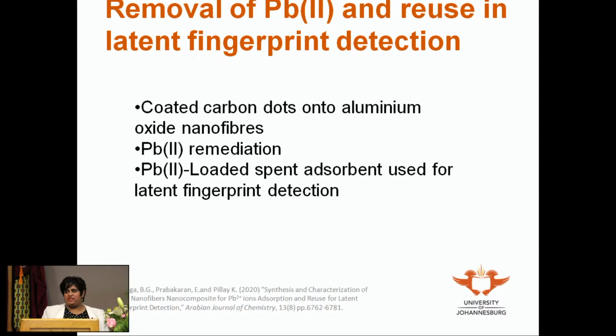Now, this has some new meaning for environmental remediation in that it can enable one to kill two birds with one stone. You're creating your adsorbent that can remove the metal ion. Then once the metal ion is entrapped on the adsorbent, it can serve as a photocatalyst to break down the organic material. Then in another parallel study, we cross-pollinated our water and forensic research. So we developed carbon dots, which we coated onto aluminium oxide nanofibers, and we used this for lead-2 remediation. And in our reuse application, we reused the lead-2 loaded spent adsorbent for latent fingerprint detection.